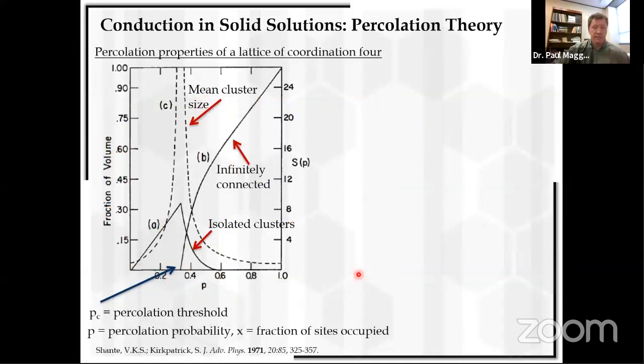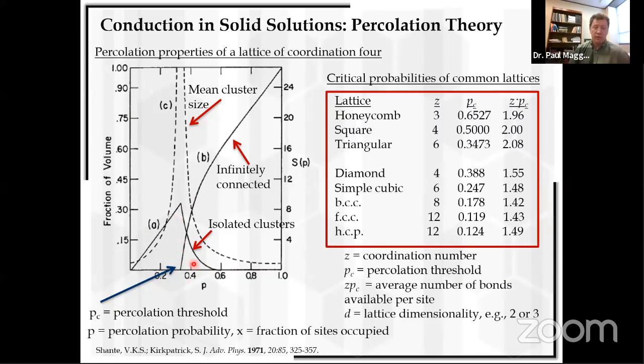And for reasons of time, I'm going to skip a little bit of this, but you can go and read about percolation theory in the relevant literature. The point at which you hit that percolation threshold depends upon the connectivity of the lattice, Z, and as well the dimensionality of the lattice. So that connectivity, Z, times the percolation threshold is approximately the dimensionality of the lattice over the dimensionality minus 1. And it's easy to calculate for simple networks.